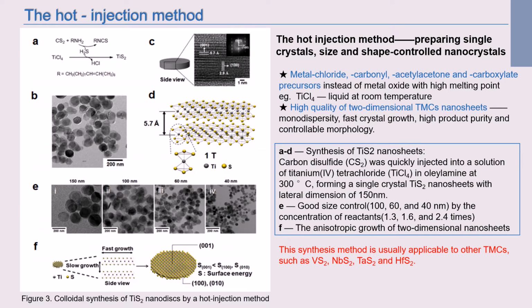Another method is the hot injection method. Instead of using metal oxide with high melting point, generally metal chloride, carbonyl, acetylacetonate, and carboxylate are employed as effective metal precursors in this method. For example, titanium tetrachloride is liquid at room temperature. And also, this method can help promote high quality of 2D TMC nanosheets. That is, monodispersity, fast crystal growth, high product purity, and controllable morphology.